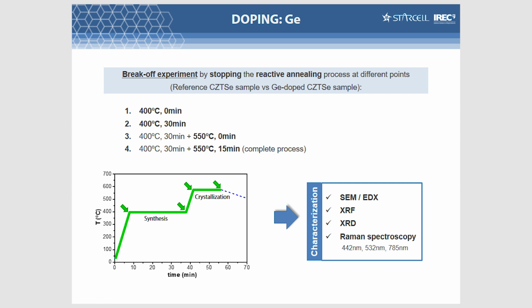This is a typical thermal routine in our lab. We start with copper, zinc, tin and germanium metallic layers, then we anneal in this two-step process. In the first step, at relatively low temperature, 400 degrees, we introduce the chalcogen, we form the precursors, and we synthesize the kesterite. Then we increase the temperature up to 550, 570 degrees to crystallize them. So stopping the reaction at different points, we can learn about what happened during the synthesis of kesterite.